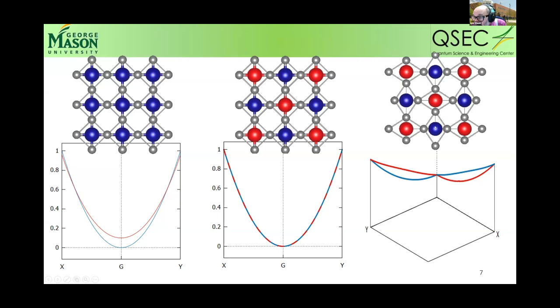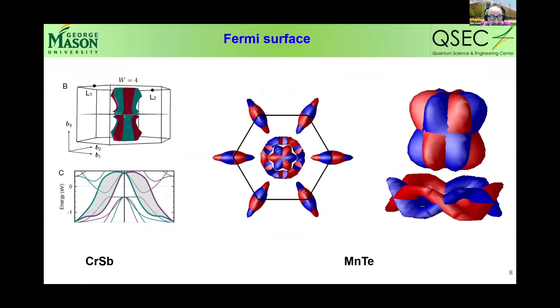But now, if we start from an atom with an opposite spin, you can see that if we go up vertically from the blue ball, it's exactly the same as going horizontally, starting from the red ball. So without any calculations, you can see that it must result in a band structure like this, where you go along X, you have spin splitting, but when you go along Y, you have the opposite spin splitting. So that's arguably the simplest possible model for altermagnetism.